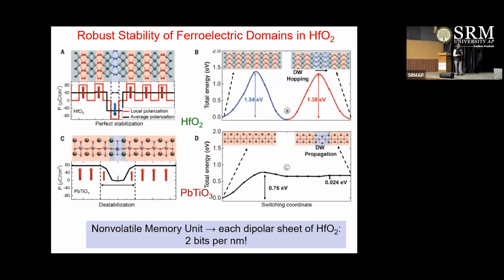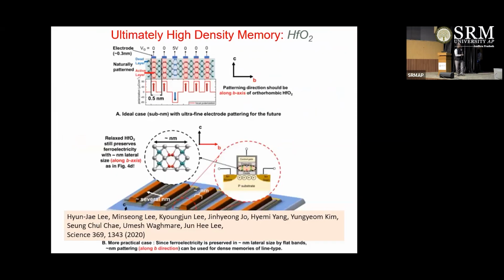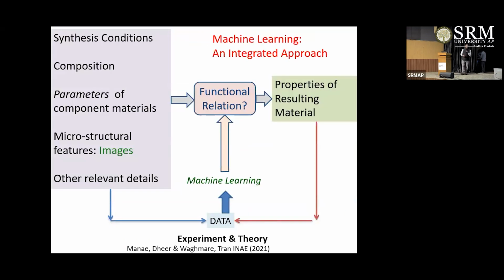So with this, you can develop computer memories, which are amazing because you don't need to nano pattern hafnium oxide. You want smaller and smaller memory devices. In hafnium oxide, you can have a single crystal with no nano patterning necessary, but you can deposit electrodes on the nanometer scale and are able to switch electric dipoles inside it. So this is a material which we believe is a futuristic material which will give rise to ultimately high memory density devices.